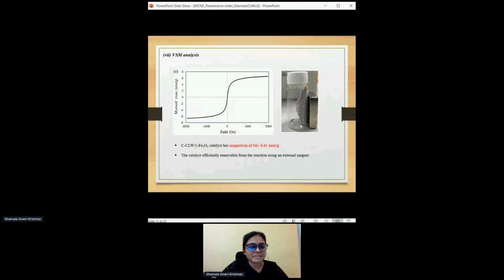And followed by that, since our catalyst is a magnetic-based catalyst, we have conducted the magnetism study, and we found that the catalyst has 6.61 EMU per gram, where the catalyst can be removed by using a strong magnet. And based on the literature review, we found that when the magnetization value is more than 4, the catalyst can be separated by using a magnet.